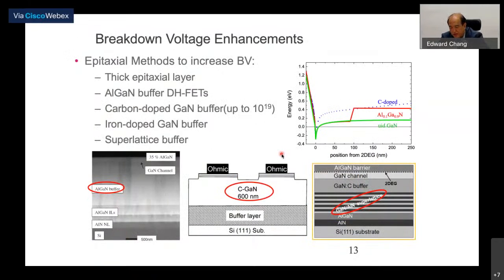So the key point here is, of course, first to grow the material with low stress, good performance, and good electrical properties. And one of the difficult parts is to grow it for very high breakdown voltage, because we are competing with silicon and silicon carbide. So you need breakdown up to, hopefully, more than 1200 volt. To do that, there are quite a few methods. For example, you can use a thicker epitaxial layer. You can use an AlGaN buffer with high band gap, and then a double heterojunction.